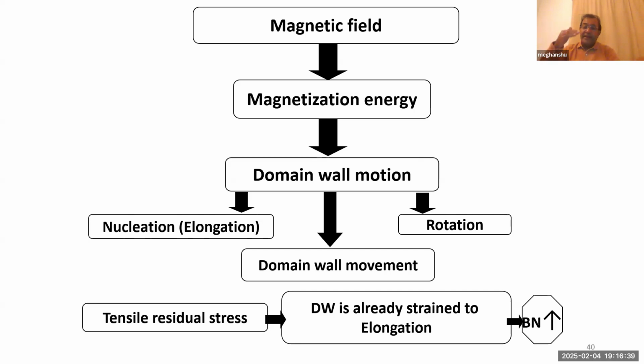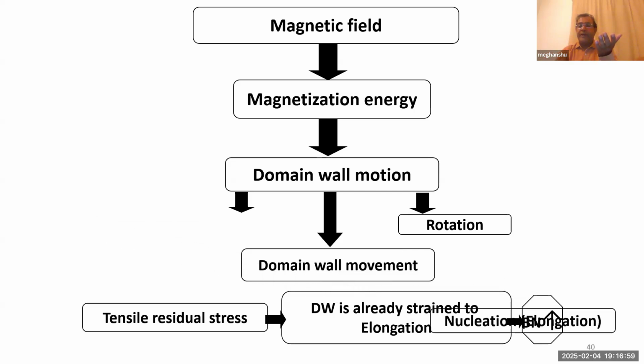Okay, I repeat, the tensile residual stress that has been induced by grinding will elongate porosity, void, grain size, and cracks, as well as the magnetic domain wall. So when the component undergoes a grinding operation, this nucleation or elongation part has been carried out by the grinding operation itself.